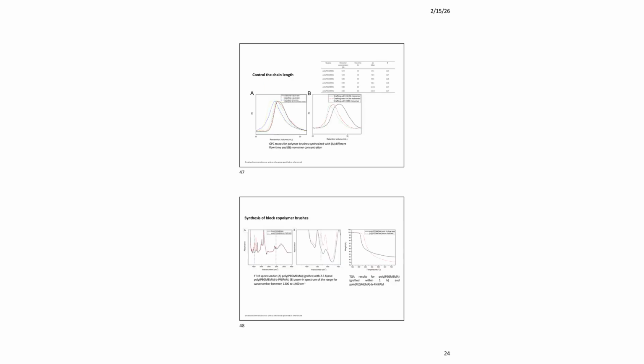Thermal gravimetric analysis, or TGA, which measures weight loss as a function of temperature, is used to quantify the amount of grafted polymer. TGA results show that the chain length can be controlled. Longer flow times or higher monomer concentrations both result in a greater weight loss, corresponding to more polymer being grafted onto the surface. GPC traces of the polymer brushes after they have been cleaved from the silica surface confirm these findings. Both longer flow times and higher monomer concentrations lead to higher molecular weight polymers, and a table summarizes this data, showing systematic control over the grafted chain length.